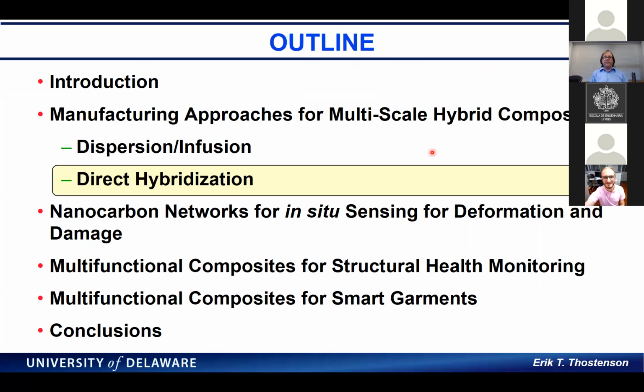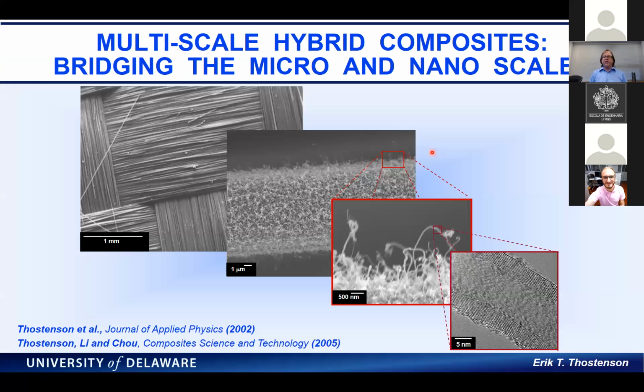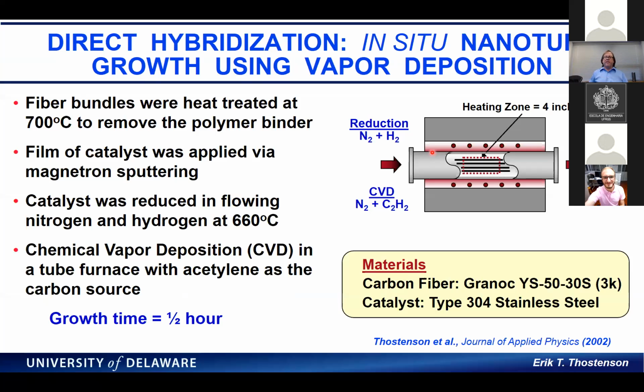The other approach is direct hybridization, and the first one that I talked about was CVD, and this is something I spent a lot of time doing in my PhD work. That's what you see, the nanotubes grown on the surface of the carbon fiber there. Basically what we do is we apply the catalyst, we heat treat the fibers, and then we put them in a CVD reactor, and we grow them under some sort of a hydrocarbon gas. In this case, we used acetylene. The catalyst we apply directly to the surface, and it takes about a half hour to grow.